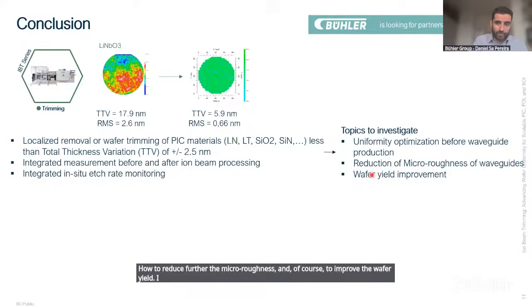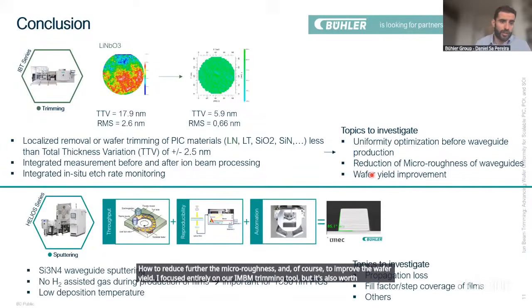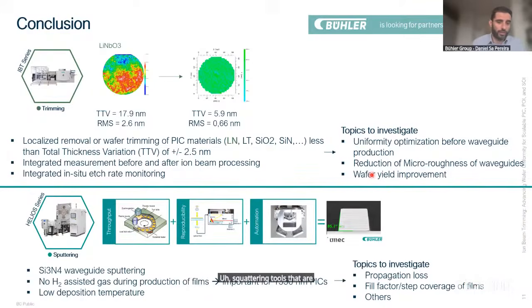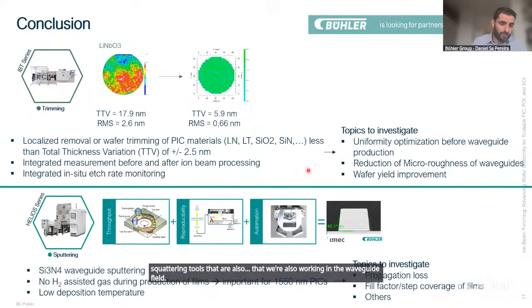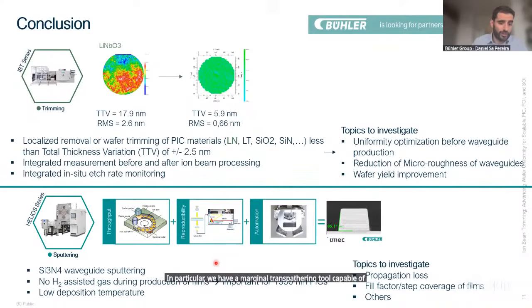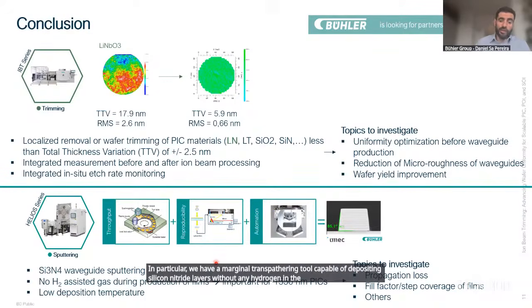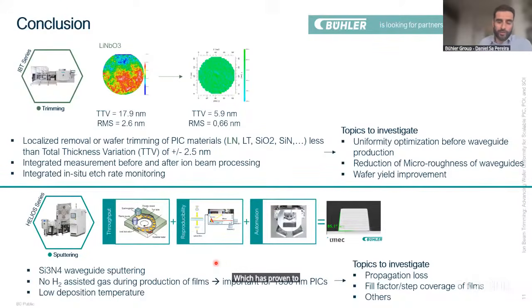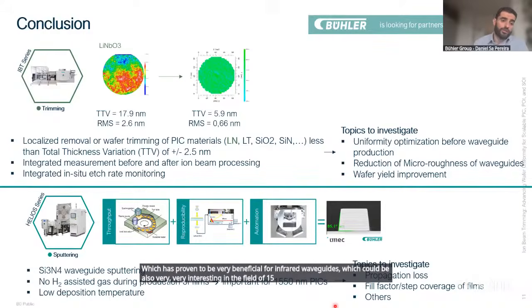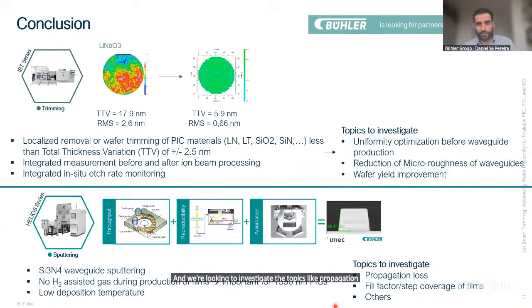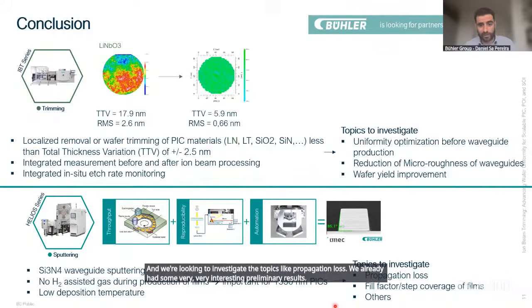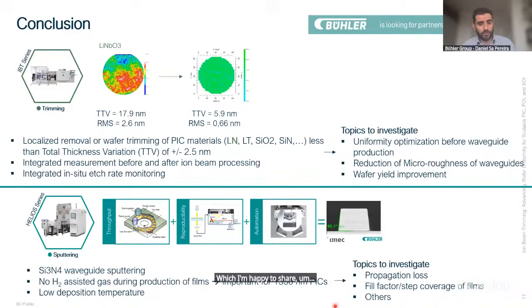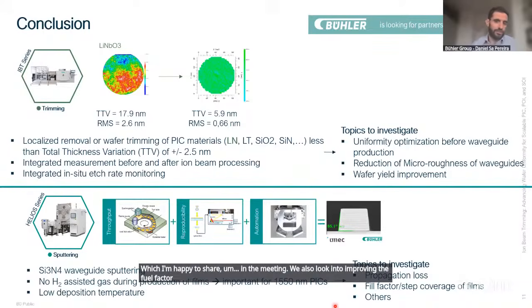I focused entirely on our ion beam trimming tool, but it's also worth mentioning that we have sputtering tools that we're also working with in the waveguide field. In particular, we have a magnetron sputtering tool capable of depositing silicon nitride layers without any hydrogen in the process, which has proven to be very beneficial for infrared waveguides, which could also be very interesting in the field of 1550 nanometer PICs. We have also developed this with semiconductor in mind, meaning low deposition temperature processes. And we're looking to investigate topics like propagation loss. We already had some very interesting preliminary results, which I'm happy to share in the meeting. We also look into improving the fill factor and step coverage of our films and other topics.